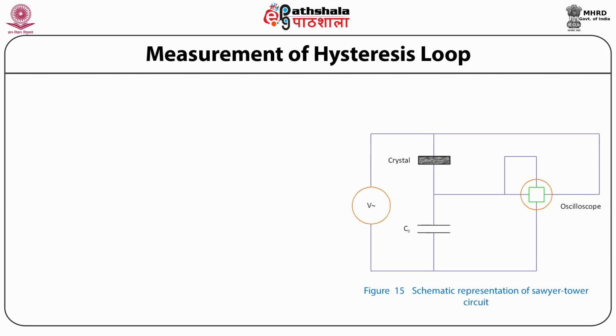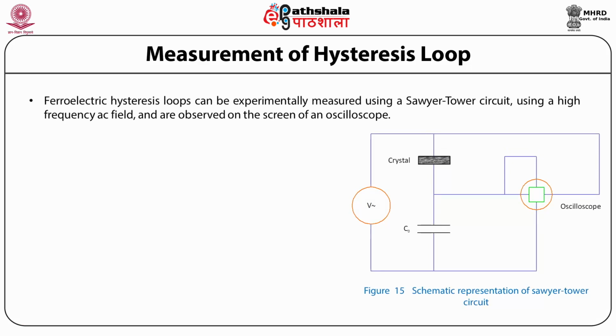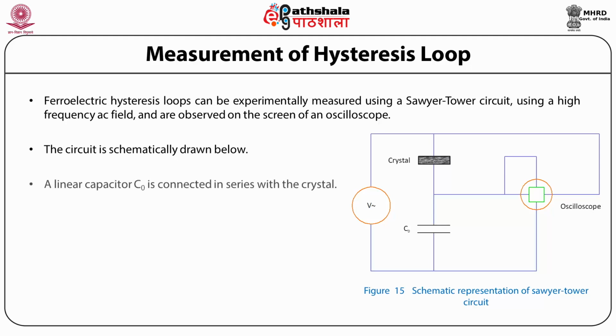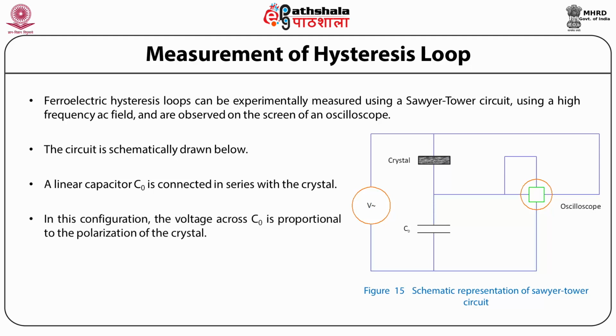Measurement of hysteresis loop. Ferroelectric hysteresis loops can be experimentally measured using a Sawyer-Tower circuit using a high-frequency AC field and are observed on the screen of an oscilloscope. The circuit is schematically drawn in this slide. A linear capacitor C0 is connected in series with the crystal. In this configuration, the voltage across C0 is proportional to the polarization of the crystal.